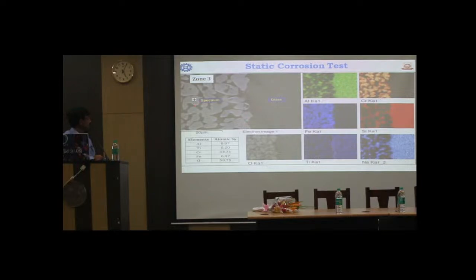This is a point analysis of the particular grain, and you see iron oxide content 6.47. So that means within the grain, iron oxide enters inside the grain. So the iron oxide forms a solid solution with that material. This iron oxide is not in the glassy phase. If you see this particular grain, all the grains, most of this white portion is black in the elemental mapping. That means the aluminum concentration is much less in that range. So there is a dearth of aluminum, but the chromium is more or less this white portion.